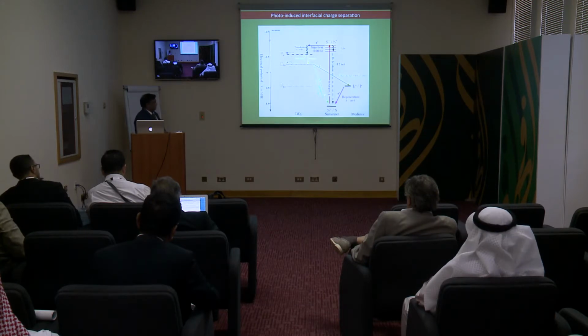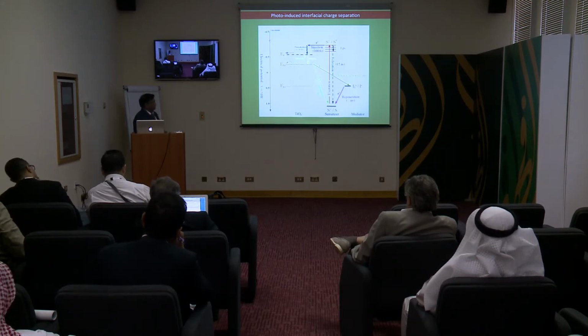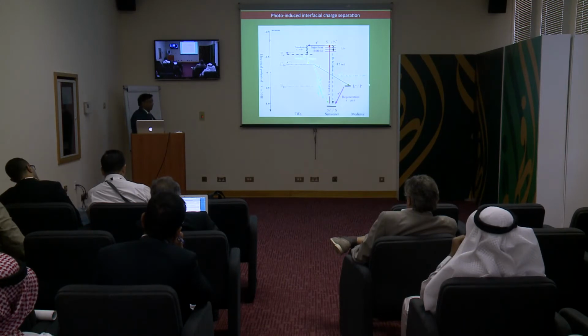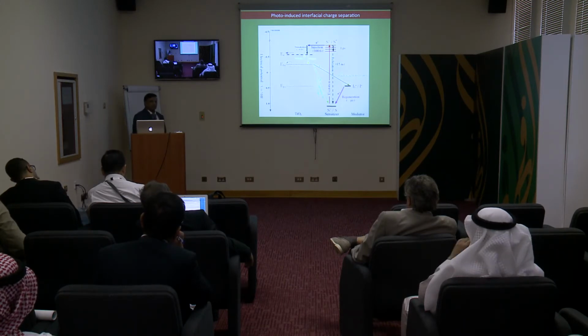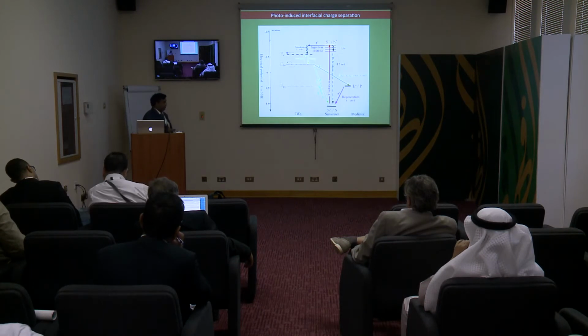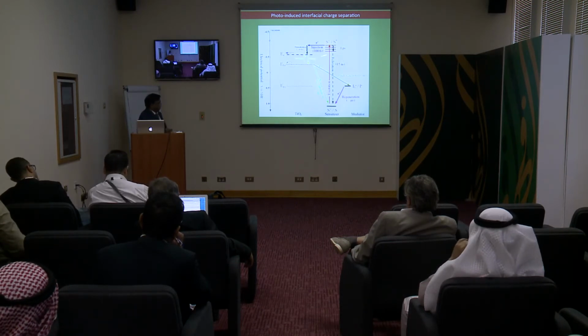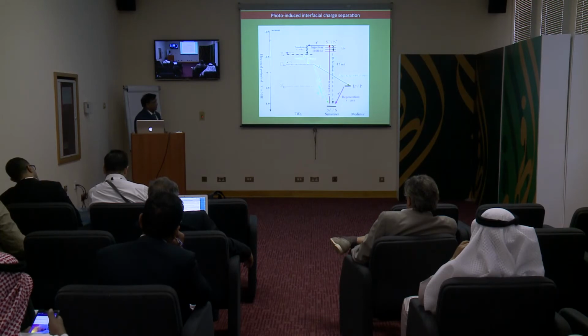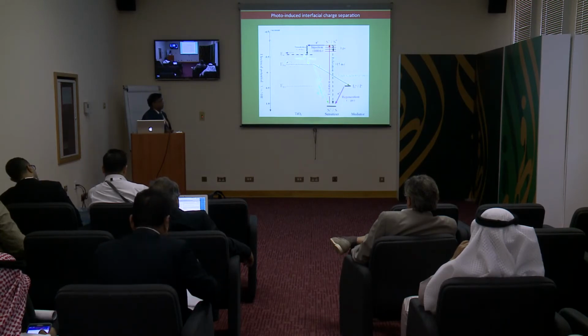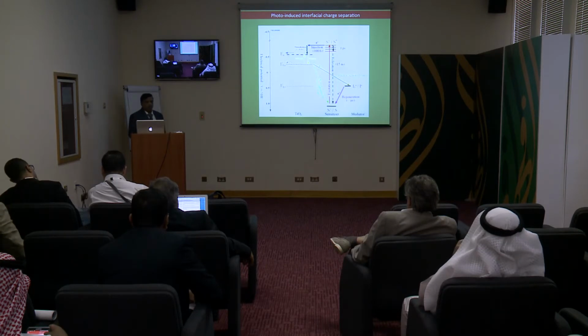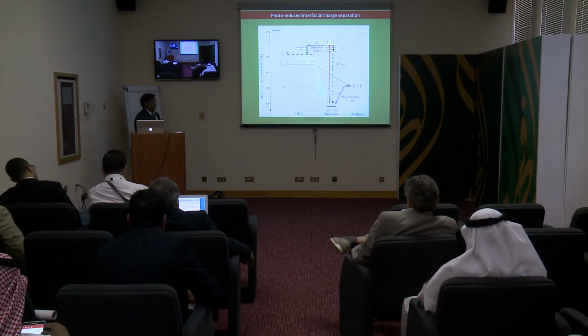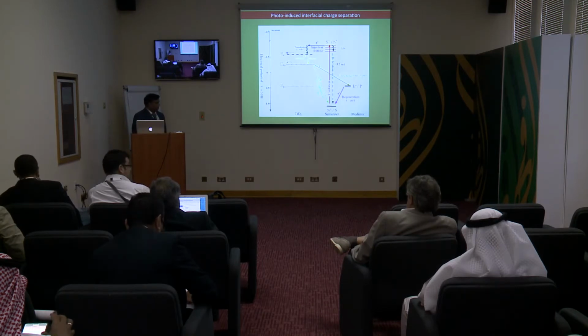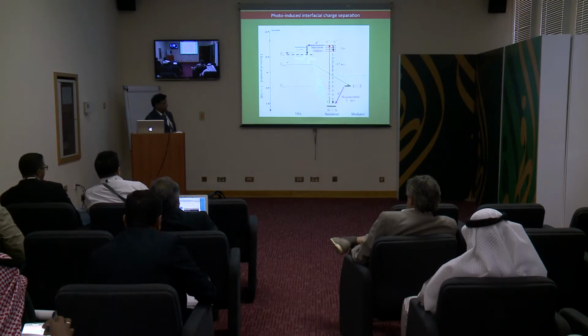And then if you look into the injected electron, there are two possibilities. You have a redox electrolyte in the system which has an oxidized species, which can take the electron from the injected electron in the TiO2, and that is called a recombination. Or the injected electron in the TiO2 can recombine with the oxidized form of the dye, which can also be a recombination process, in the millisecond time scale. But these two reactions are competing with the dye regeneration because it's a very fast reaction, happening on the microsecond time scale.